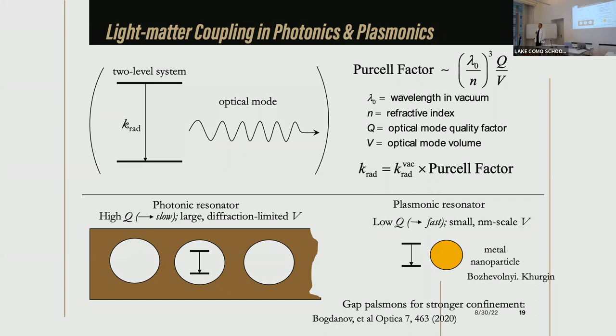And there are two different approaches to realize Purcell enhancement. One which is pursued by 99% of all groups. It's basically to use so-called dielectric cavities. The idea is very trivial, actually. Normally, coupling of light to matter, to a qubit, is very small, simply because the size of the wavelength is much larger than the size of an atom. So there's a huge mismatch, and therefore coupling is naturally small.